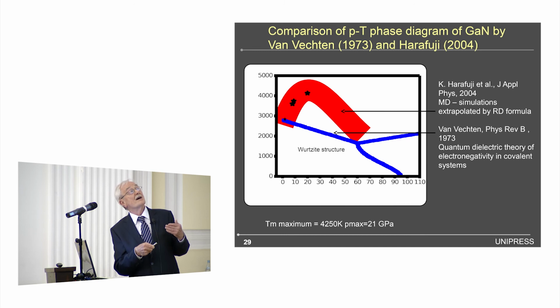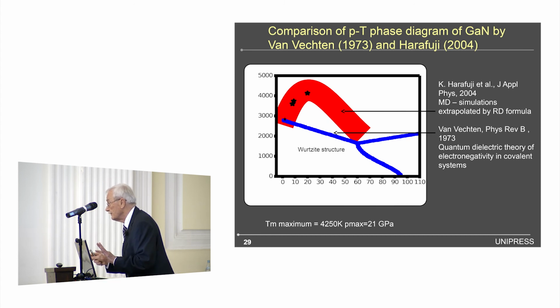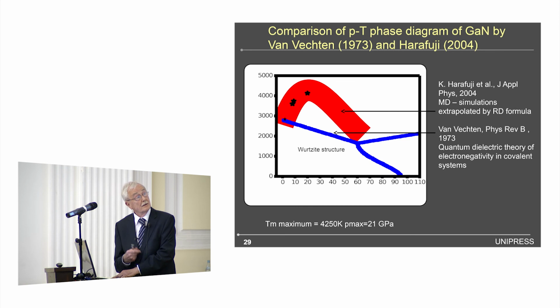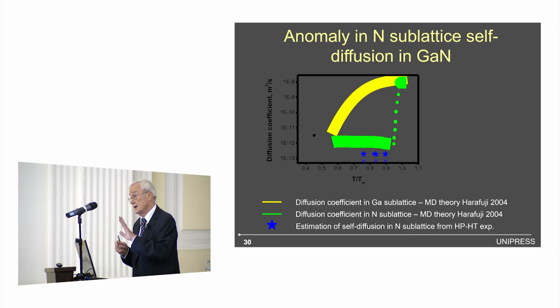And for this kind of dependence, we know that at these pressures, we have the low density liquid, and at here, we have high density liquid. So that's one mystery, and you see this theory is also able to predict other very anomalous dependence of gallium nitride.